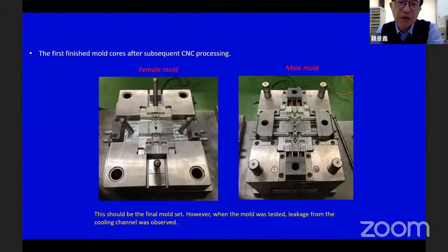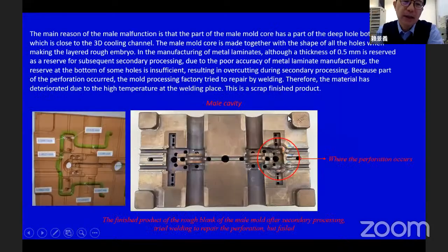But unfortunately, when we performed the mold testing, because this was the company's first time to fabricate this kind of core, they made some mistake. There was some leakage from the cooling channel. They tried to fix the problem, but unfortunately they could not fix it.